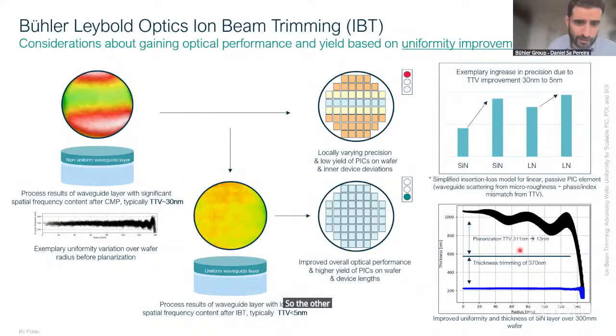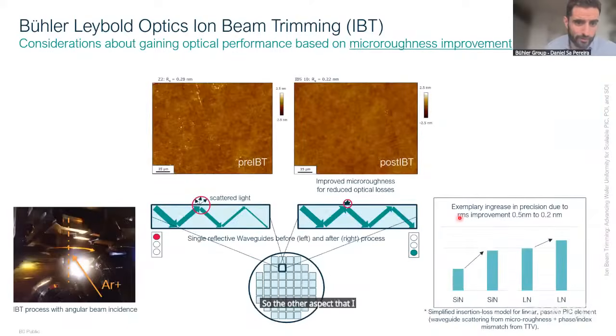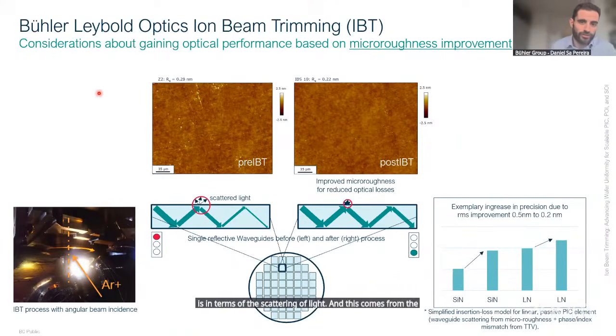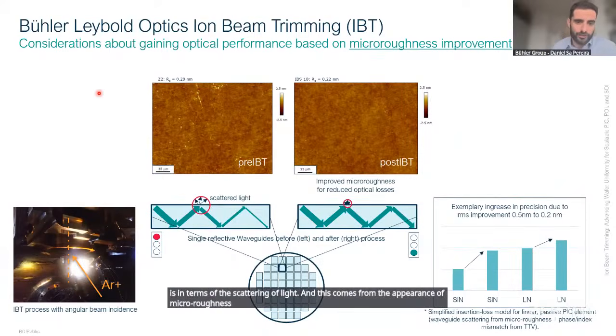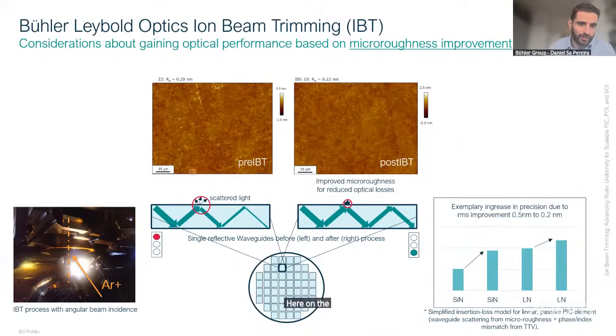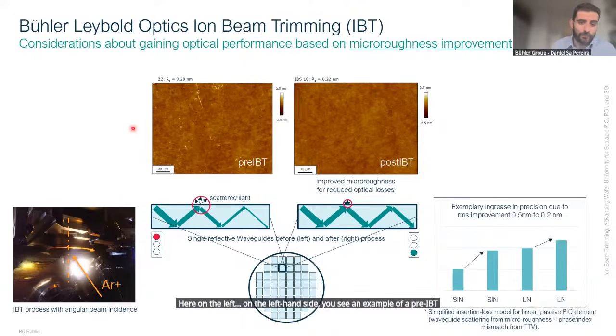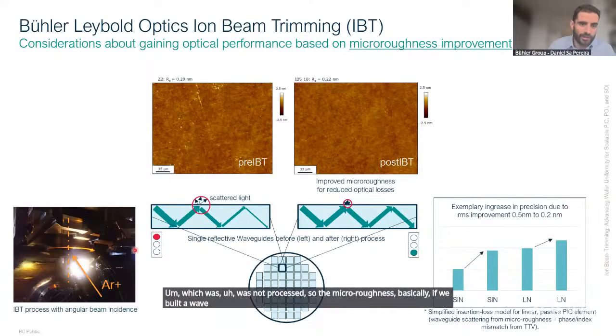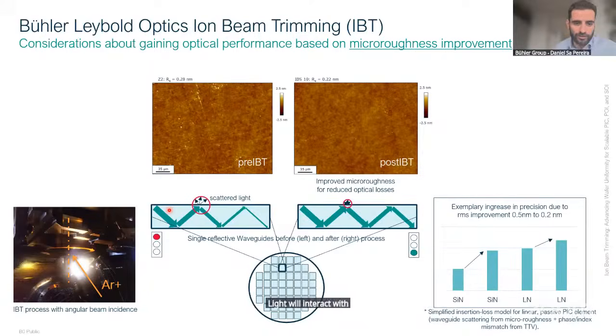So the other aspect that I mentioned in my slide before is in terms of the scattering of light. And this comes from the appearance of micro roughness on a wafer level. Here on the left-hand side, you see an example of a pre-IBT material, which was not processed. So the micro roughness, basically, if we build a waveguide out of it, light will interact with these microstructures and will scatter the light. The end result is that the propagation of light will be reduced.